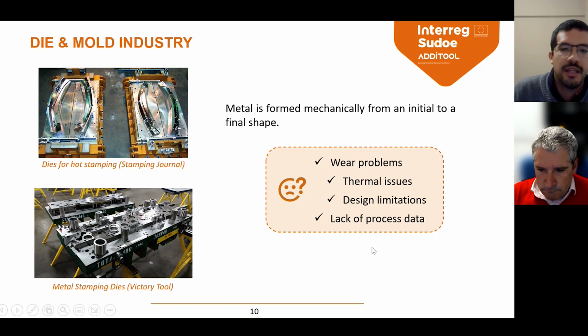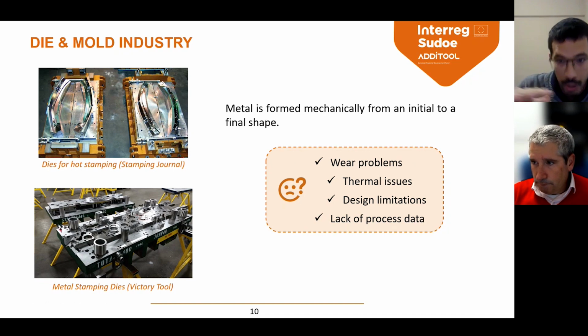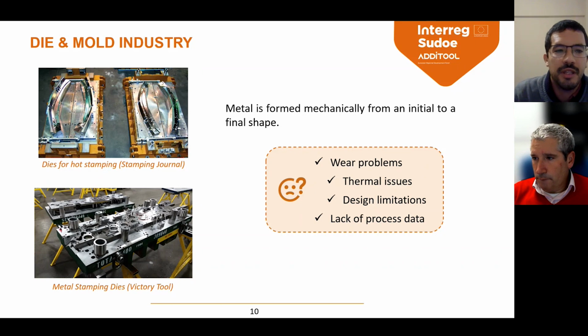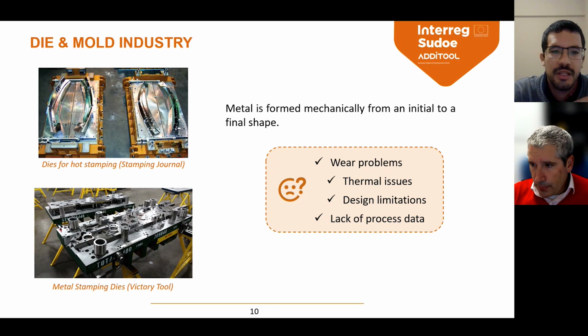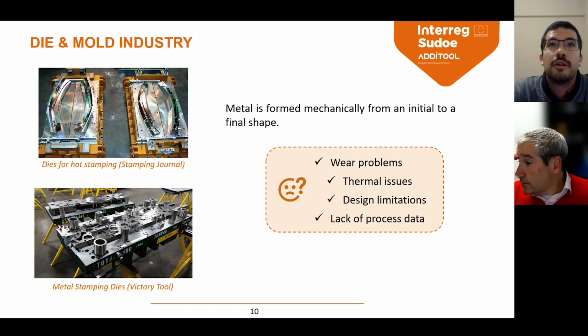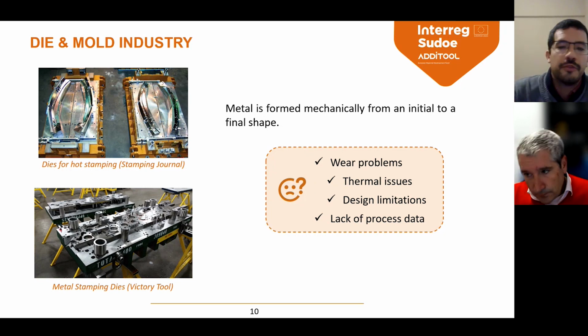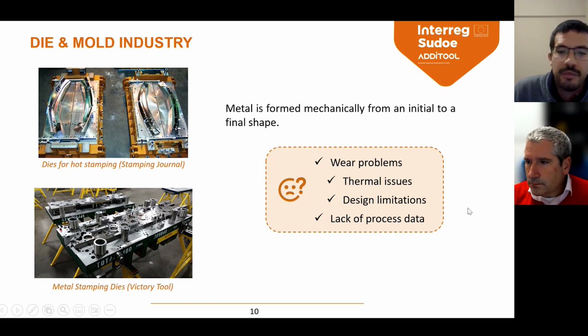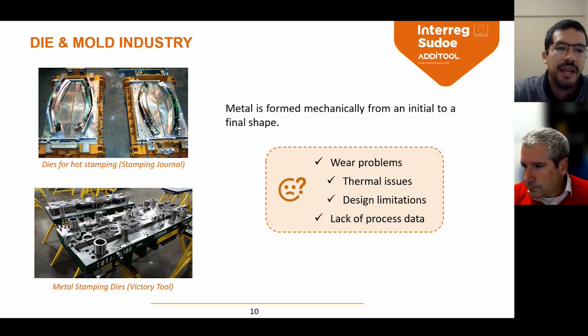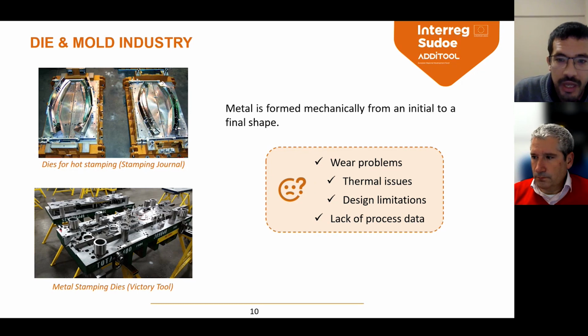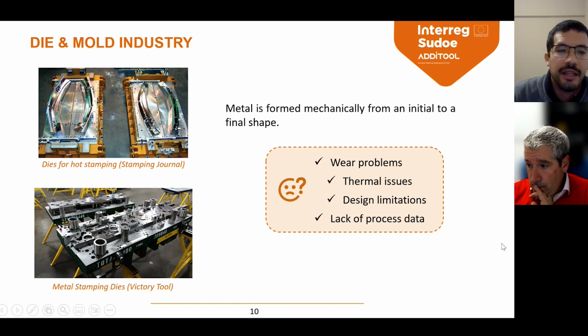And we have identified some typical problems in all those processes, which are wear problems because of the friction between the blank or the part and the tool faces. Also thermal issues in case of hot stamping because of the high temperatures developed during the process, which may decrease the properties of the tools or also generate abrasion problems. Also, for hot stamping, we have some design limitations due to the geometry of the cooling channels, which are typically manufactured by drilling, and somehow their shape is restricted, which is always straight. And finally, we have also identified a lack of process data directly in the forming area. Let's say that it's easy to monitor the process in the stamping press, but it's not so easy to obtain information about the blank which is being formed during the process.